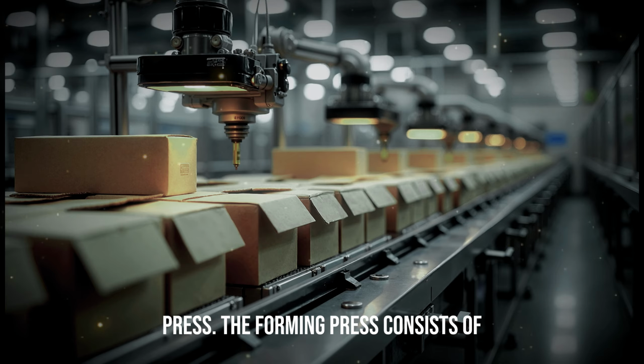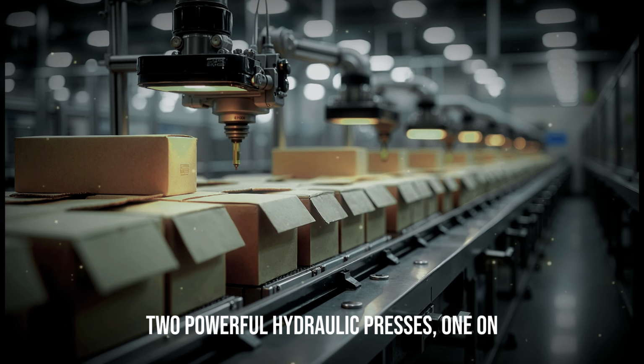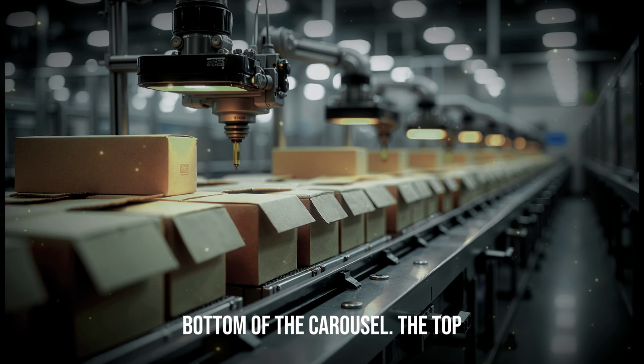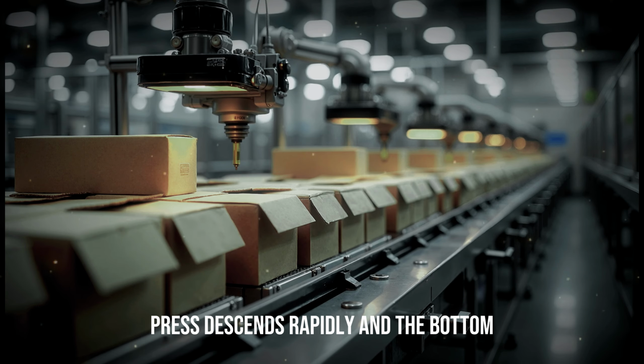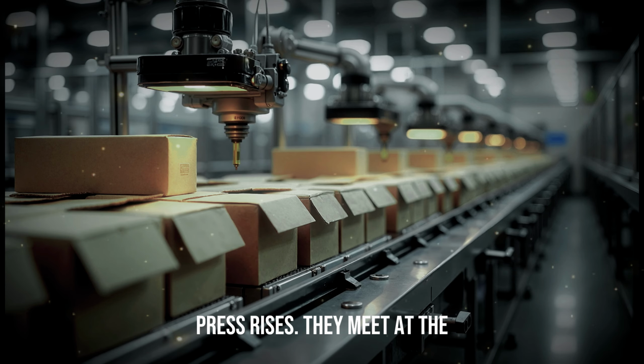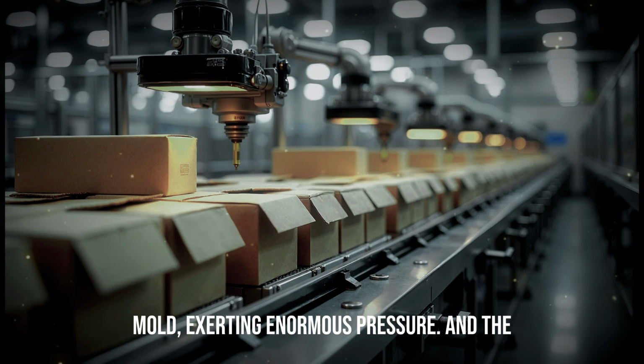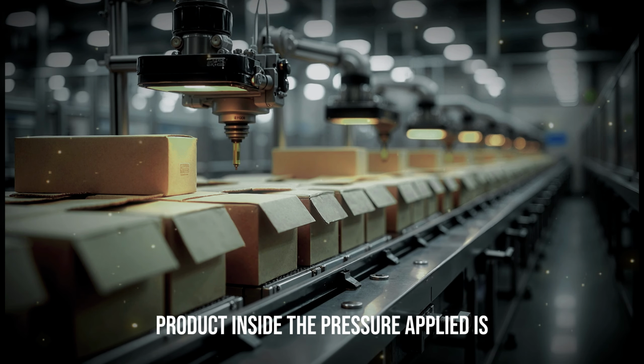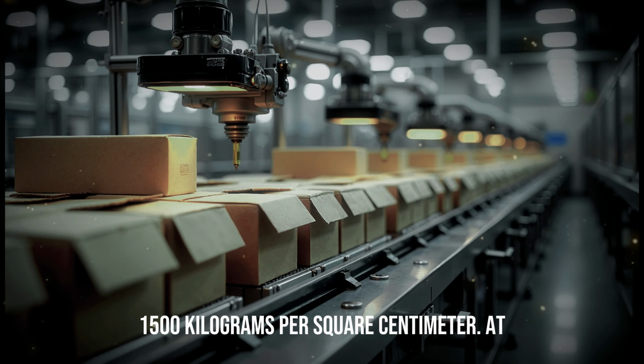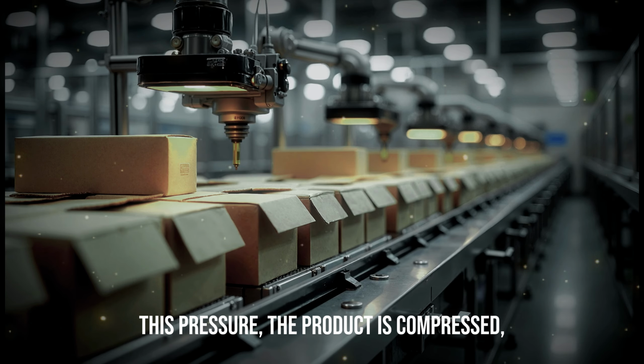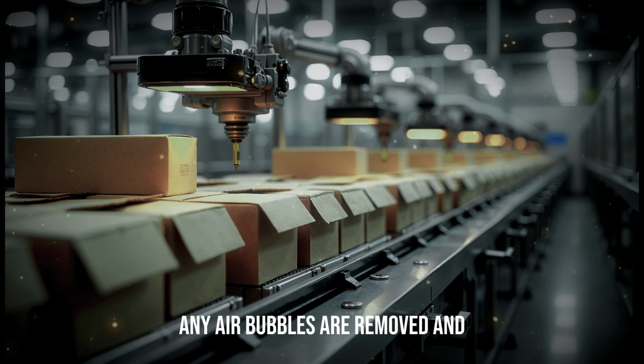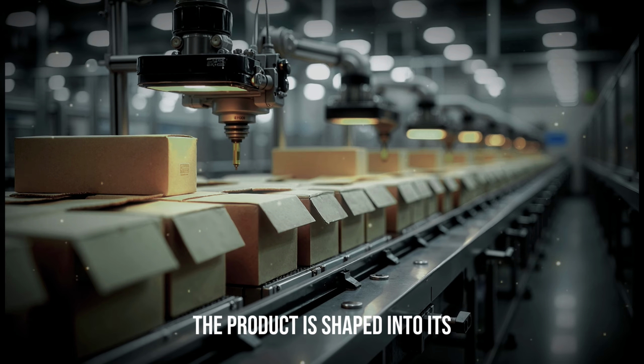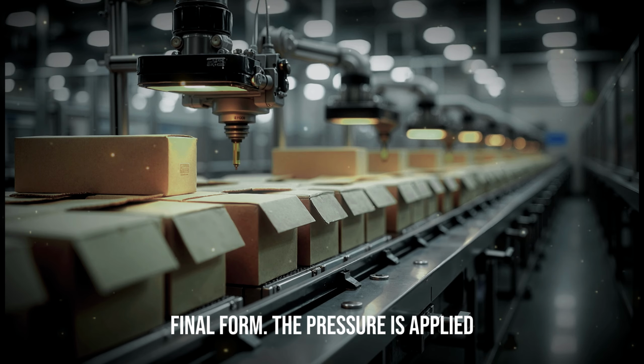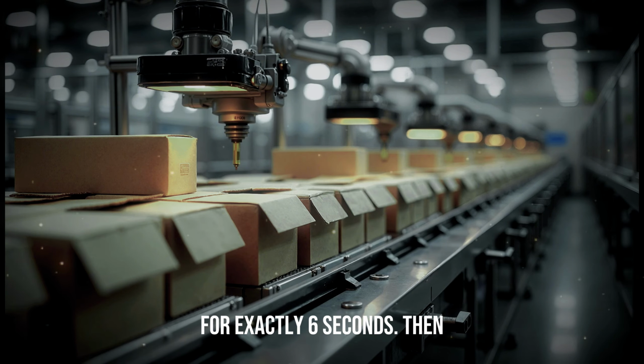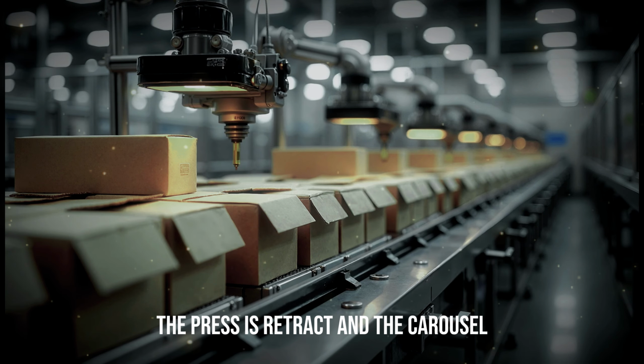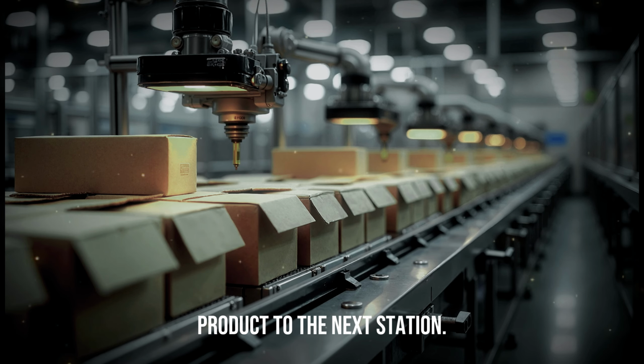The forming press consists of 2 powerful hydraulic presses, one on the top and one on the bottom of the carousel. The top press descends rapidly and the bottom press rises. They meet at the mold, exerting enormous pressure on the product inside. The pressure applied is 1,500 kilograms per square centimeter. At this pressure, the product is compressed, any air bubbles are removed, and the product is shaped into its final form. The pressure is applied for exactly 6 seconds. Then the presses retract and the carousel rotates again, bringing the formed product to the next station.